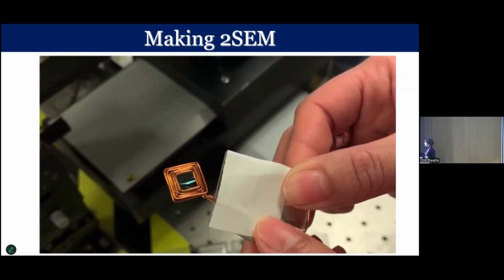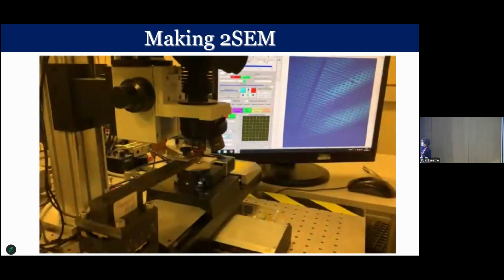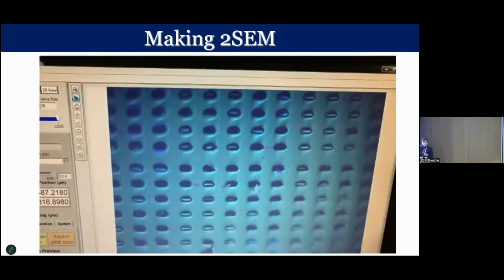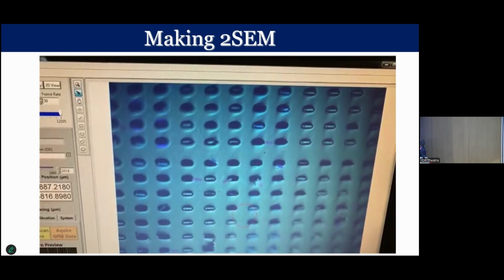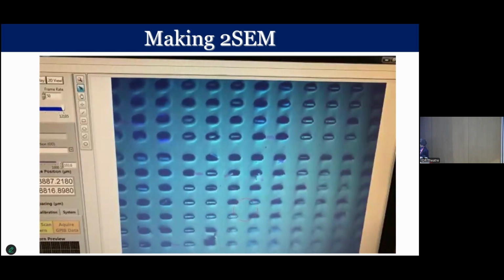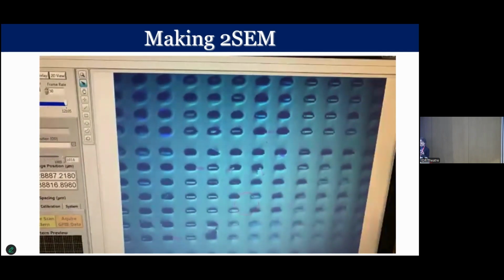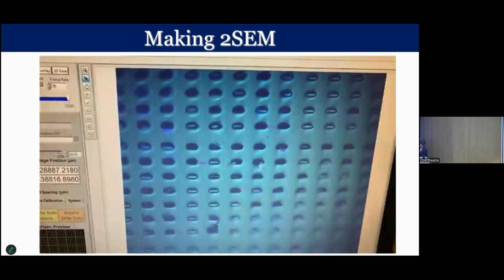And here, in the centre of this copper coil, are the CVD graphene strips that we'll be using to transfer onto our substrate. Through the microscope, we see this dotted pattern, and each one of these dots, in theory, is where there should be a graphene strip. You can see the individual strips here in this close-up, and each strip is about 10 microns wide and 40 microns long. The graphene is covered by PMMA, which makes it easily visible under the microscope.